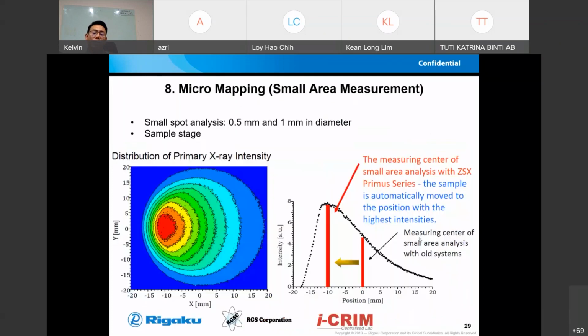Okay, so just now I think quite a lot of people were asking: what is the possibility of measuring a small area of a sample? The answer to all those questions is micro mapping. Even though it is called mapping, you don't really need to do a mapping if your sample is very small. The smallest spots available in the Primus 4 are 0.5 mm and 1 millimeter in diameter. If your sample is bigger than or equivalent to this size, you can also do this kind of measurement. If your sample is a little bit curved, because the part that we are measuring is very, very small, the curvature might not affect it so much.